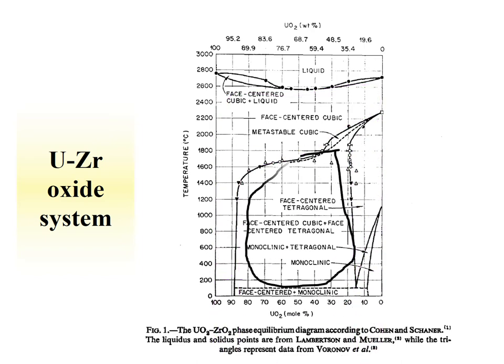Now, in this regime shown here, we have multiple phases formed, face-centered cubic and face-centered tetragonal. So when we started to reach percentages of uranium that were lower than what's shown in that solid solution regime, we start having mixed species. Now this is an example of a system that's important for nuclear fuel. As zirconium is a large fission product, it's also been explored for inert matrix fuels, but this system is also rather complicated and you can find different data in the literature.